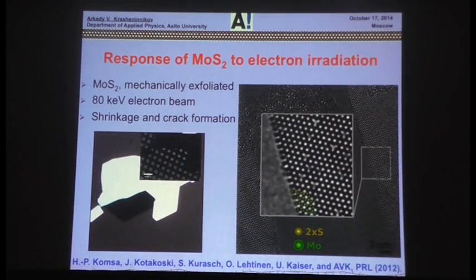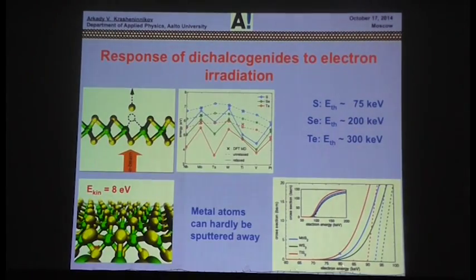Now let's go back to dichalcogenides. Again, a couple of years ago, our co-workers saw these vacancies and they asked us where these vacancies come from. To answer this question, we calculated formation energies of vacancies in different dichalcogenides, and also calculated displacement thresholds. Once more, the displacement threshold is the minimum kinetic energy assigned to the atom so that it leaves the position and goes to infinity. If the energy is not enough, it goes back, and then using the binary collision formula,